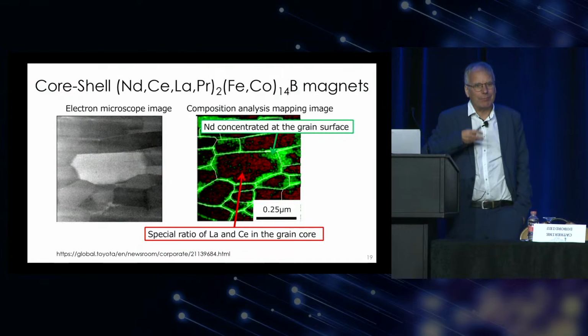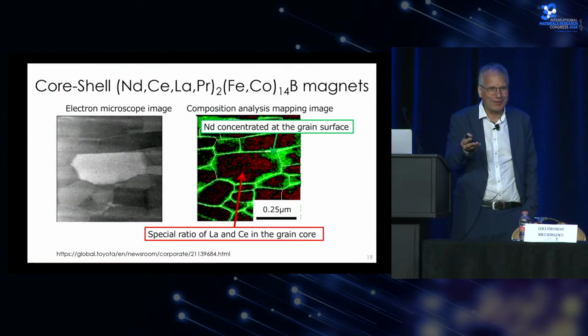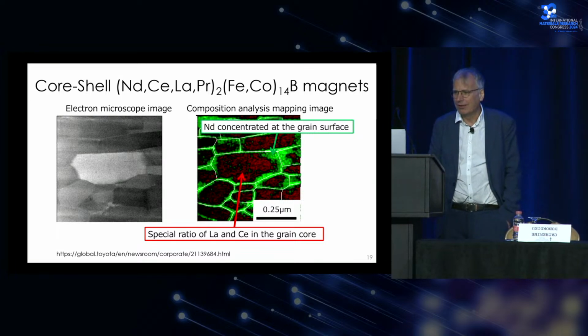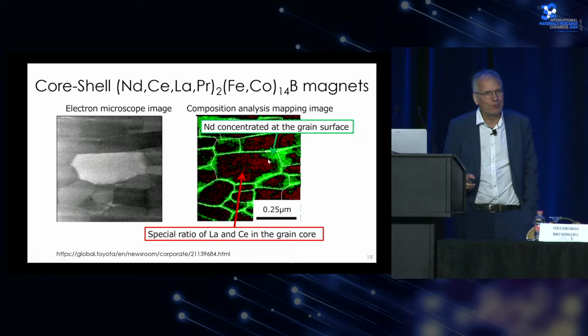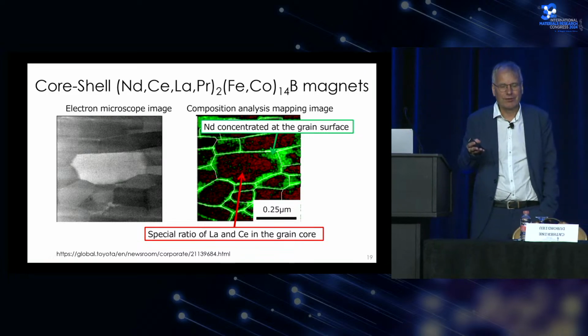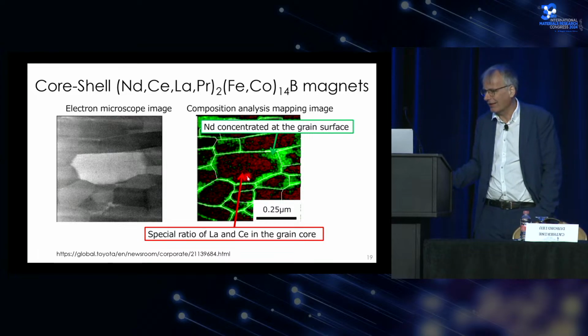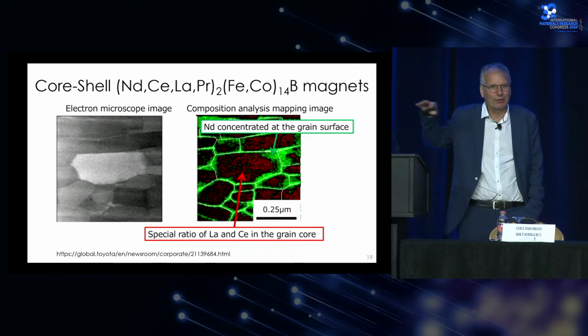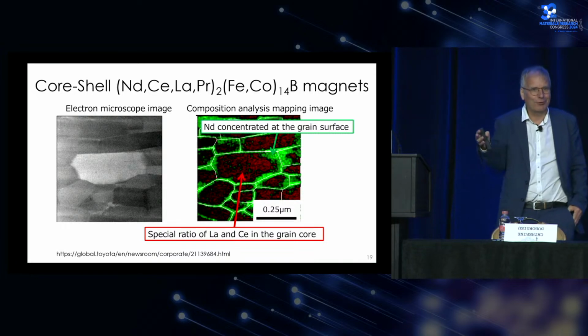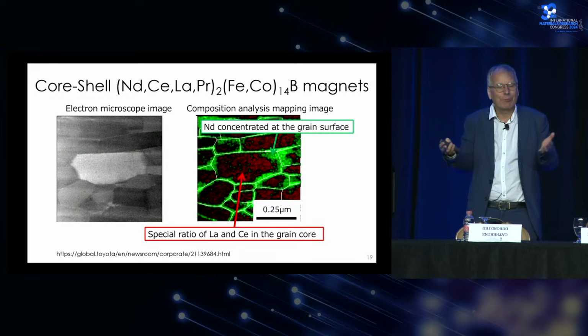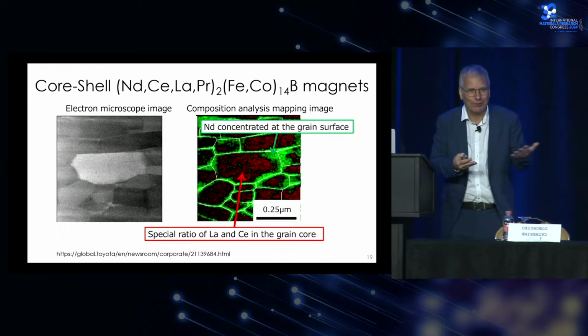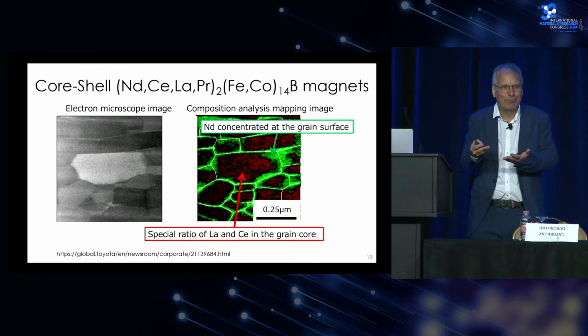Yeah, that's a very good question. So let's maybe go to this slide here. So indeed, we make a prediction and we don't tell how you can produce it. What we know, for example, in this case, is that the core shell structures are obtained by grain boundary diffusion. So you start with a material that only has the cerium containing grains without neodymium, and then you put neodymium copper on the surface and let it diffuse. And there is a lot of data already on this diffusion process. But we haven't matched these two things together, so that we also know what processing parameters I need to get a certain structure.